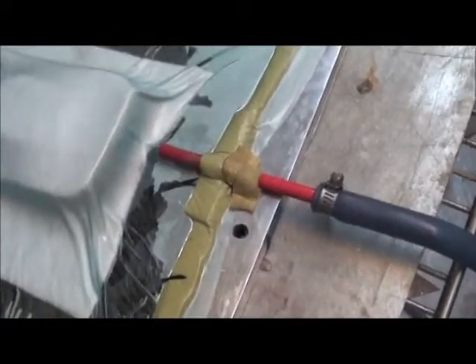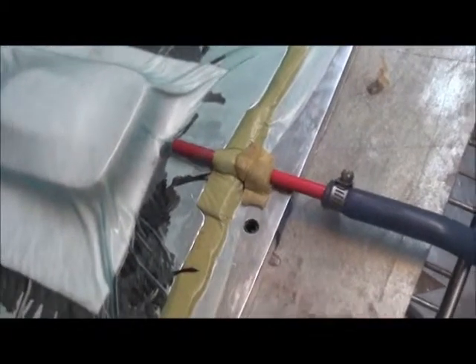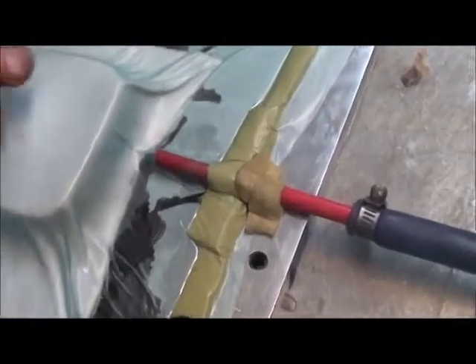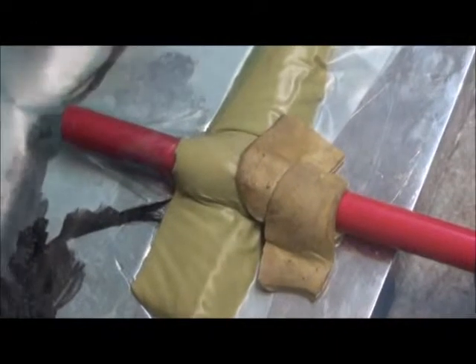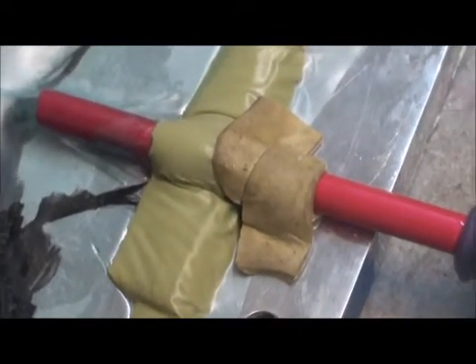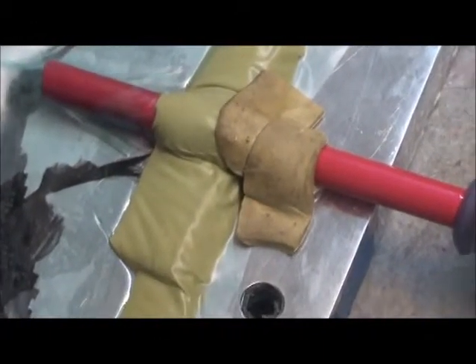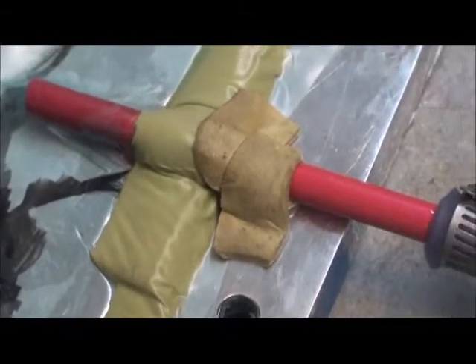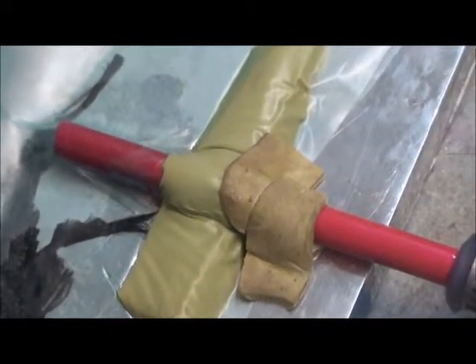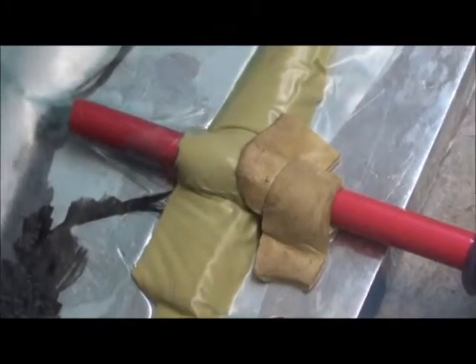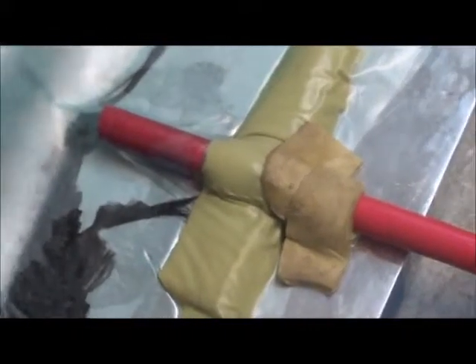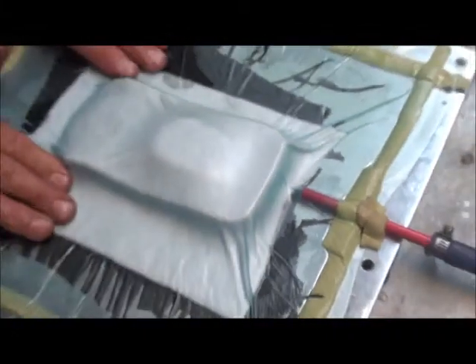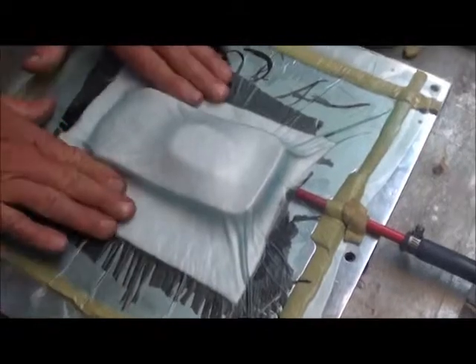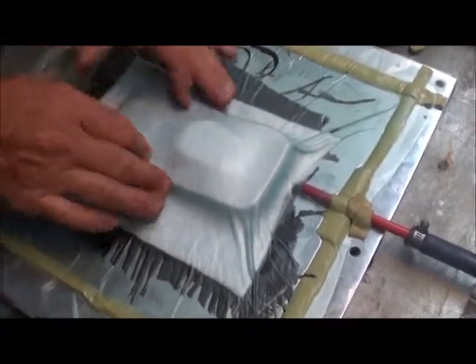Okay, so we found the leak. We were at 15, 16. And we found that right there, by using our ears, we were able to find the leak and then plug it up. And then instantly when we plugged it up, the vacuum jumped from 15 up to 20. So then we knew we had it. And that's going to give the part a complete profile.